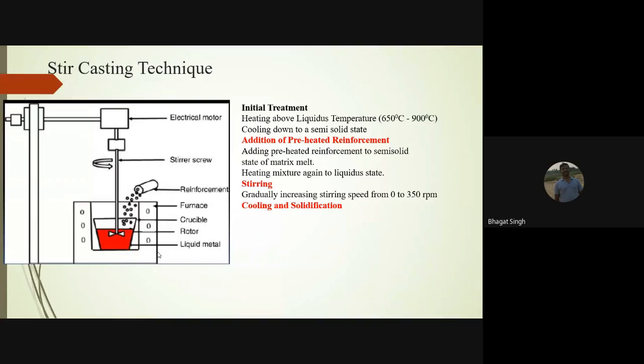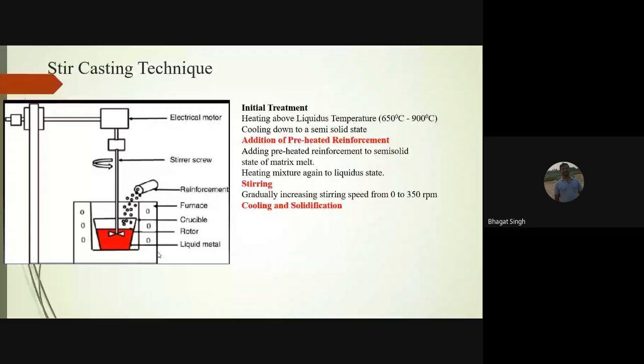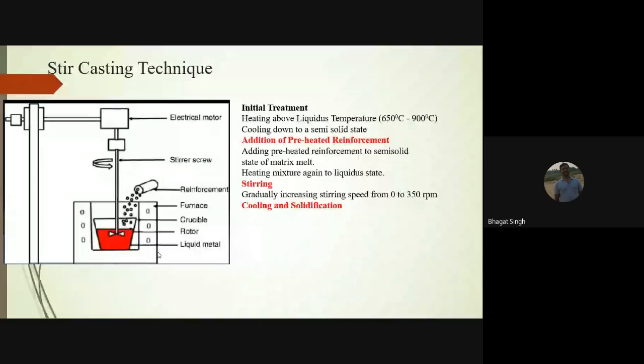If you are going for making any automobile engines, definitely we have to use the casting method. There is no other manufacturing method available for manufacturing automobile engines. So here also we have used the stir casting technique, which is a very well established technique for the manufacturing of composites. The crucible is heated above the melting temperature. For this work, we heated the aluminum 5083 alloy to 700 degrees Celsius. During the heating of the base material, we preheated the basalt powder.